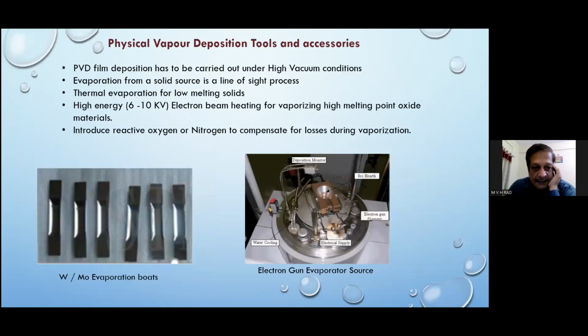Here I am showing certain sources. Here for thermal evaporation, we use molybdenum evaporation boats. And on the other side, I'm showing this electron beam deposition system. Here we see the hearth is there. In that the material is put. And then you can see the power supply. High voltage is coming through these two leads. There is a tungsten filament here, which is heated, and the electrons are accelerated. And there is also a hidden magnetic field, which is not shown here. It is covered. So that magnetic field bends the beam and heats the material.